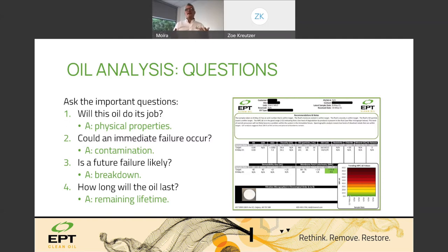And things like RPVOT, that's a great example actually. This is a very expensive test, and that could be maybe $400. And if there's not a reference guideline to that test, then any result is meaningless. Certain oil tests can only be interpreted relative to a standard as a reference point. And if that doesn't exist, then you can't get any value from that number, because the number is completely meaningless without that reference point, okay?